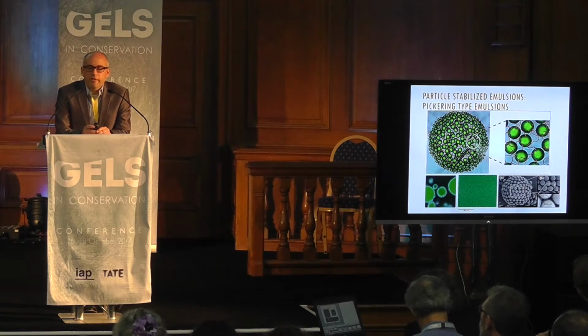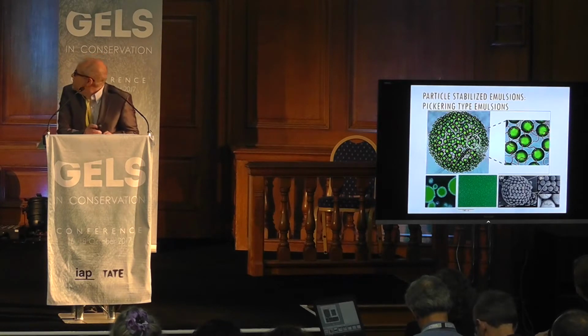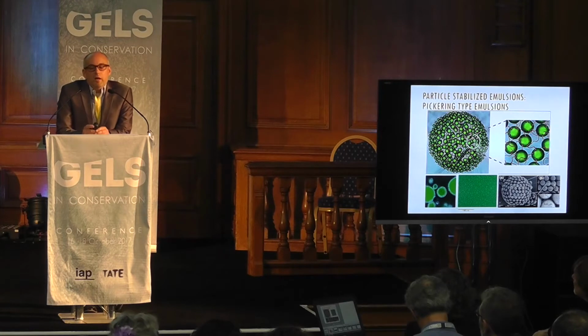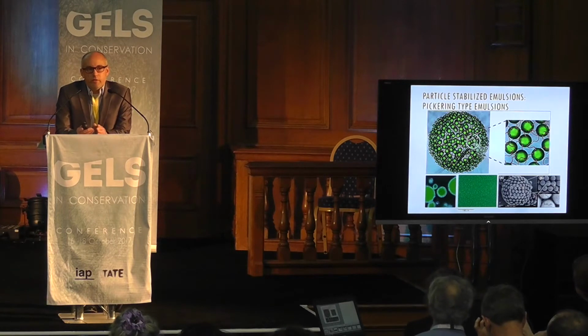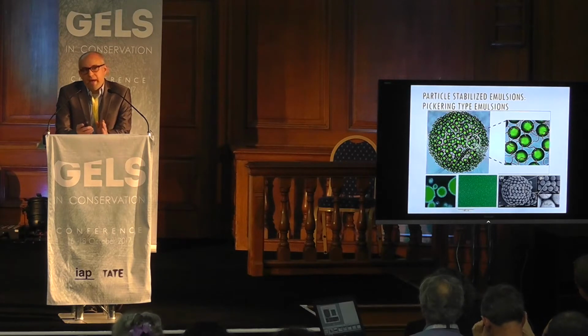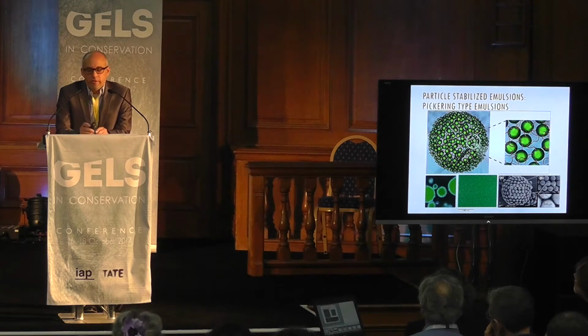So in the lower left-hand corner, you can see the division there. Those particles surround an aqueous core. So they wet 90 degrees into the aqueous phase and 90 degrees into the silicone solvent, and hold water trapped and hold it back from a surface. We're going to have to make that water work to get at the surface to clean these paint films.